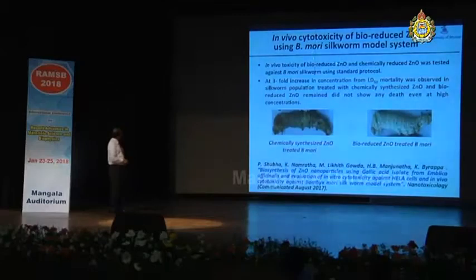And we have tested the cytotoxicity in vivo for this bioreduced zinc oxide using this B. mori silkworm. As you can see here, this is the chemically synthesized zinc oxide treated B. mori, and you see the mortality here, and here the bioreduced zinc oxide treated B. mori, and this survives longer, and the bioreduced zinc oxide did not show any death even at higher concentrations. That is what we have observed in this.